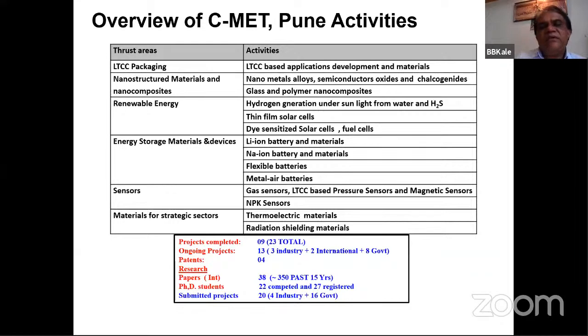So we designed a photocatalytic process at room temperature. We get hydrogen using the photocatalyst, like semiconductor photocatalyst that we are going to see in some of the slides. And from water, we get hydrogen and oxygen. And in H2S, we get hydrogen and sulfur, very colloidal, very small particles of sulfur. We get the decomposition, which can be used for agriculture purposes.